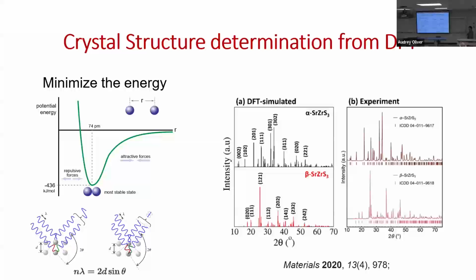So first we find the structure and then look into properties. This is the first step: we have to optimize the structure. Based on the material, we may have to use different functionals. If you have layered materials, then you have to use, let's say, a van der Waals functional, so you have to add that dispersion correction. And if it is magnetic, then standard DFT may not be enough, so in that case we have to use some correction. There is an on-site Hubbard correction term, and we can use that as well. And if it is strongly correlated, then we have to use that or approaches beyond DFT.